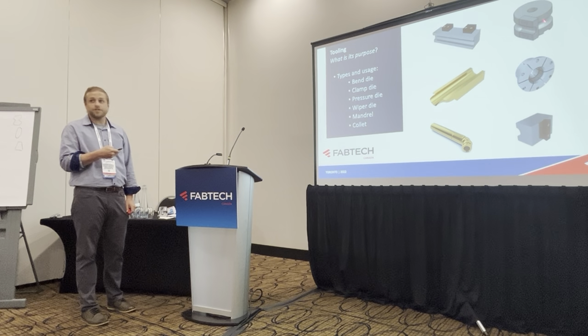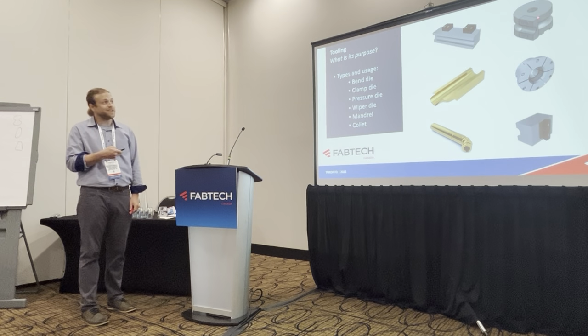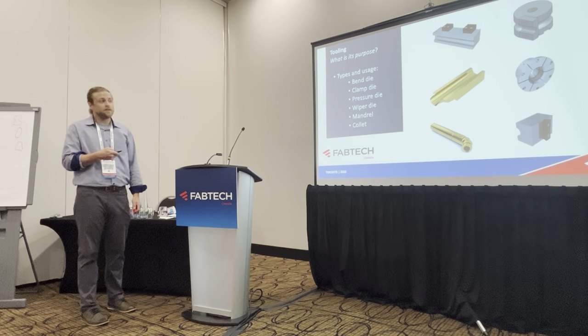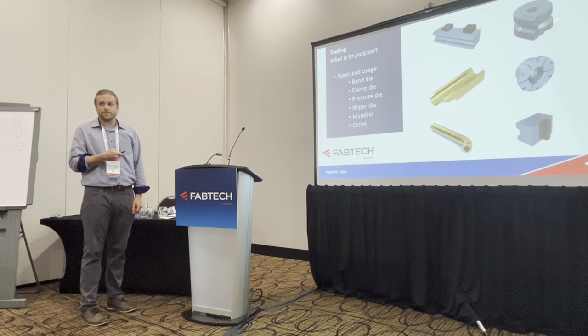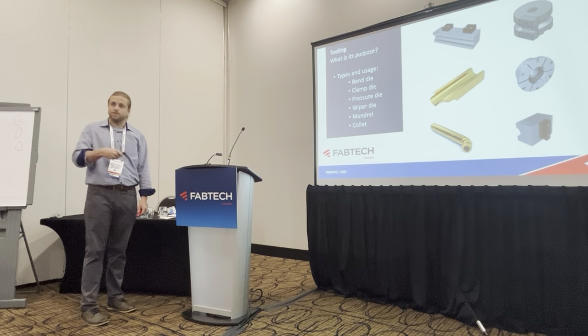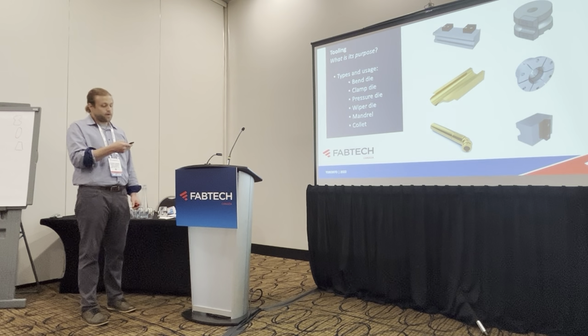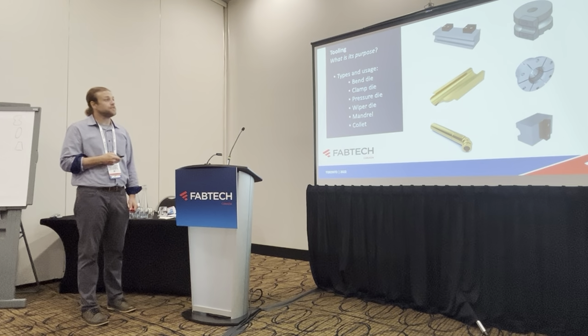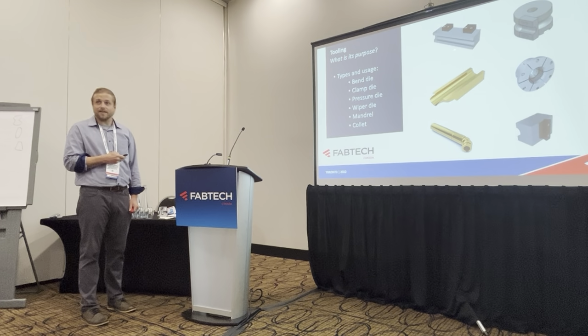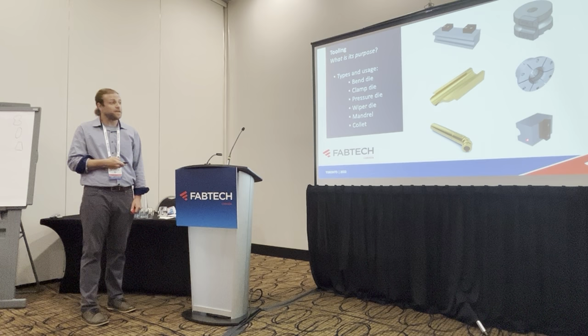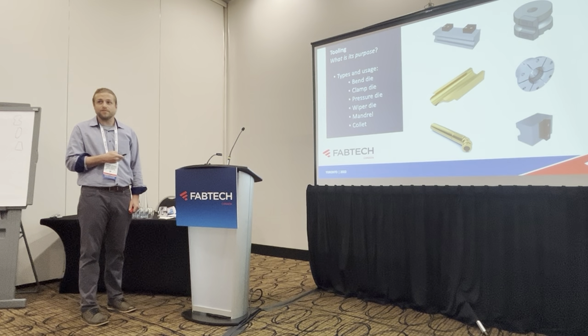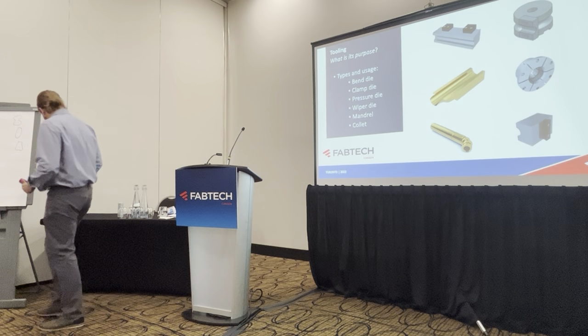You can either have this be interchangeable, or you can actually machine it hard into the die for a specific job. And if you machine it into the die without it being an insert, you add rigidity to the die. So you want to usually not use an insert on those tighter bends, like as you move down towards a 1D bend. You're going to want to look at more so a machine insert. So what happens in the bend process, this pressure die rides on the back end of the tube following the clamp die. So as this clamp die is pulling the tube around the post and bend die, this pressure die follows, keeping the back side of the tube from kicking out.